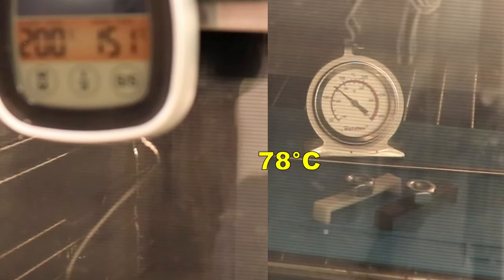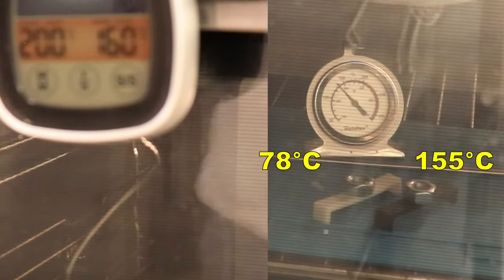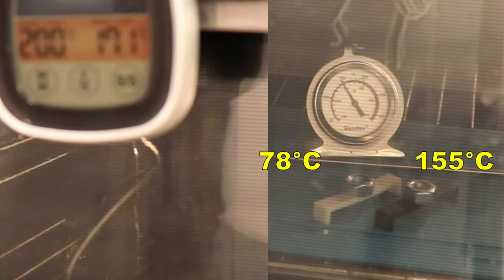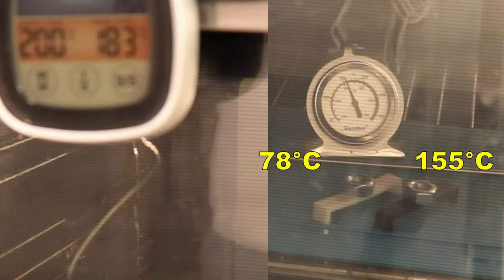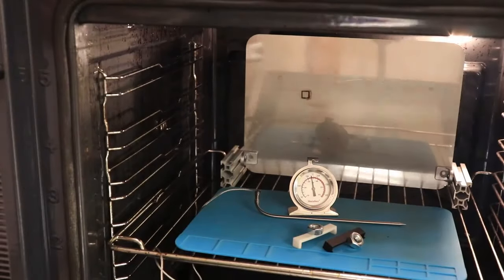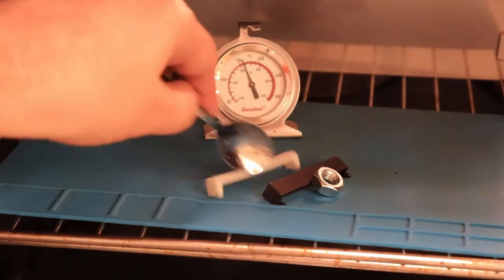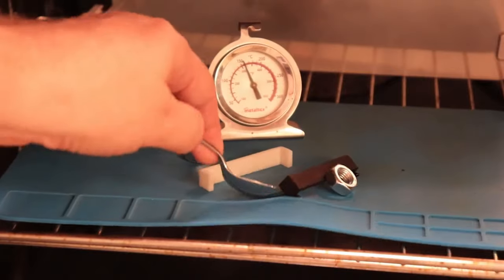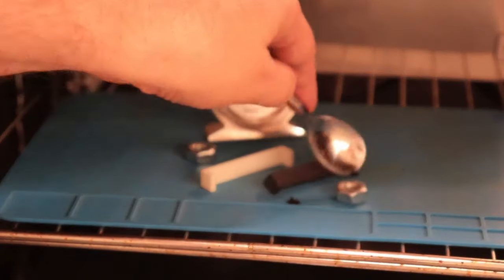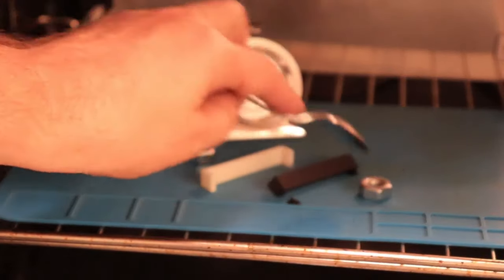And only at 150 degrees Celsius approximately I noticed first deformation of the nylon, but it started here with the melting, but I couldn't notice the bending under the screw nut. 192 degrees Celsius, I will stop the measuring here. The nylon melted partly.